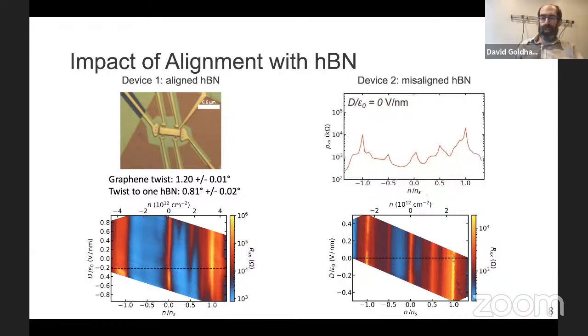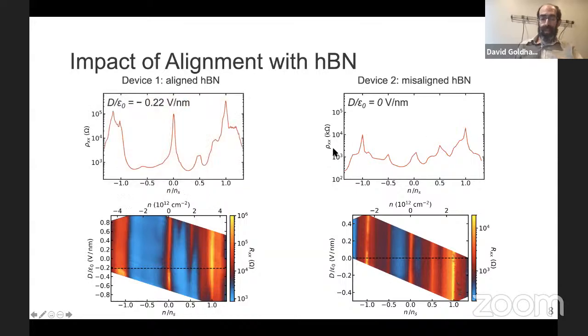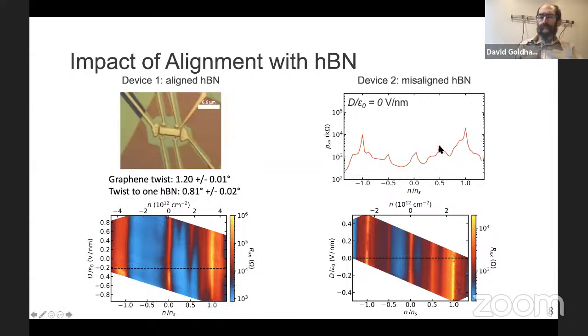So I apologize for the coarseness of these data. I haven't replaced them with more recent ones, but what you can see here is that at the charge neutrality point, there's a peak in resistivity. And there's a peak when you have the band completely filled or completely emptied. And then there are peaks also at half filling of the upper part of the band. But if you look at these resistance levels, as I mentioned, they're relatively modest. In this case, say 2 kiloohms. So 2 kiloohms is a fine resistance value for a graphene sheet.